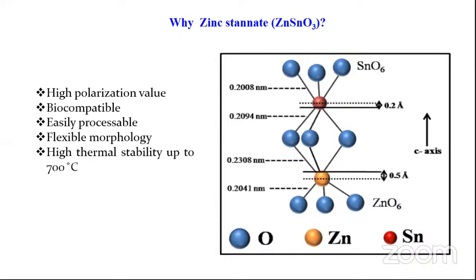If you look at the crystal structure, each crystal structure contains two types of octahedra. One is SnO6, another is ZnO6. In SnO6, the Sn atom is displaced by an amount of 0.2 angstrom, whereas in ZnO6, the zinc atom is displaced by an amount of 0.5 angstrom. So basically, it's an asymmetric structure, and that asymmetric structure produces a polar axis, the polar C axis. That polar C axis is responsible for the high polarization value, and this is also biocompatible because of the presence of zinc and tin atoms in the zinc stannate nanoparticle.